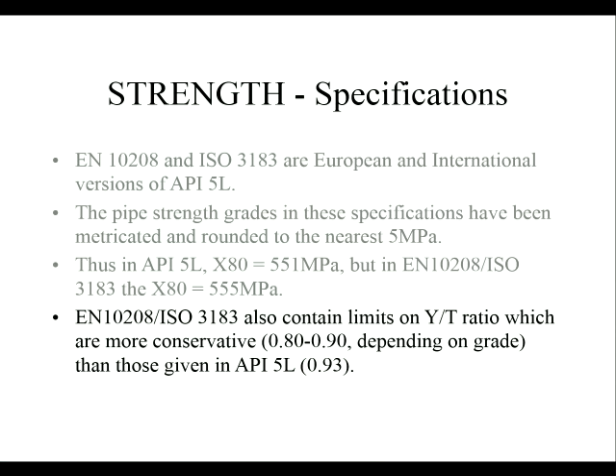ISO 3183 contains a limit on the yield stress to ultimate tensile stress ratio, which is more conservative than those given in API 5L, typically around 0.9 as opposed to 0.93. So what that says is that we don't believe in Europe that you can go as close to the limit with these materials as the American API 5L system will say. You need that extra work hardening in hand to allow for overstress beyond the yield stress limit. It's not a big difference, but it can be significant in some cases. So that's one of the things that I think is a difference between the standards, and the ISO standard is marginally better. But again, it's not a big deal.